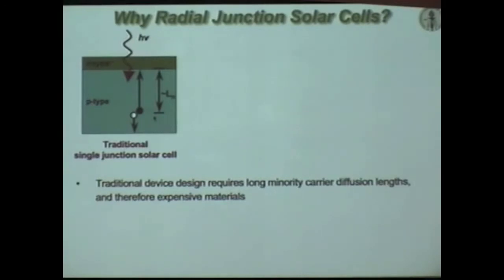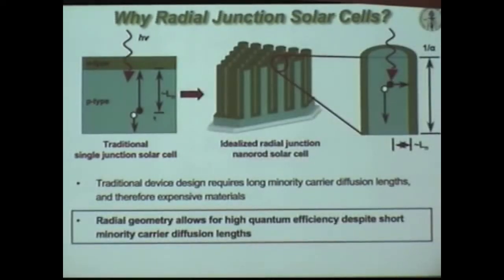So this was an unsolved problem that we decided to change the rules, and therefore we might be able to change the solutions. The way you would change the rules is you still need 300 microns length to absorb the light, but if we want to make really cheap silicon, for instance, or other materials that have short diffusion lengths, let's just make the carriers go sideways only the short distance that they can go, and orthogonalize their direction of collection relative to their absorption. If you change the rules, you can open up a whole new set of design principles. And that's why the rod structure was on that napkin.